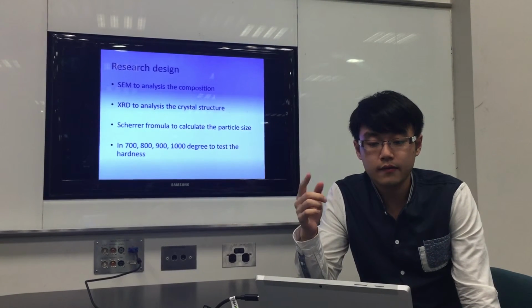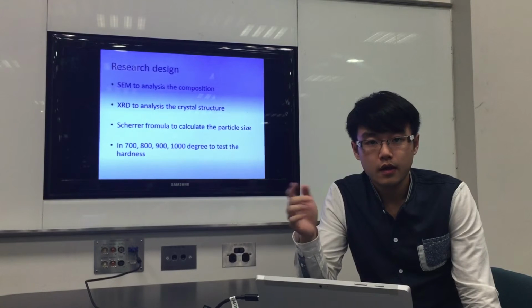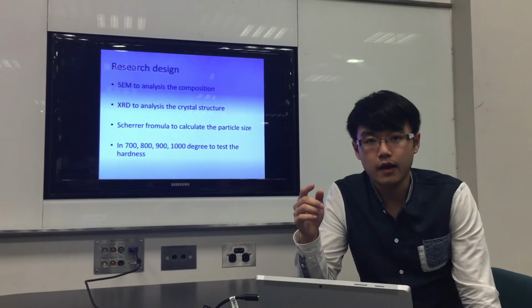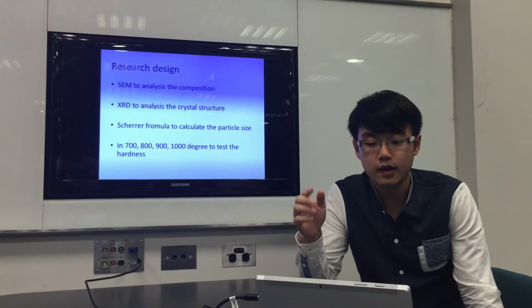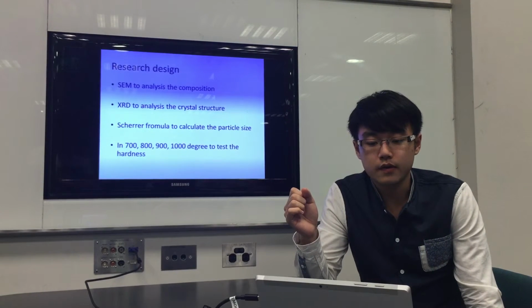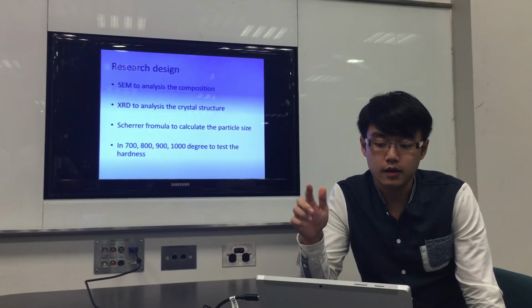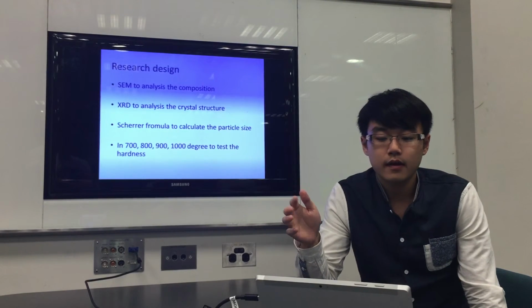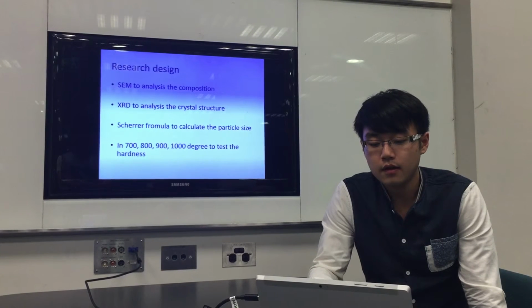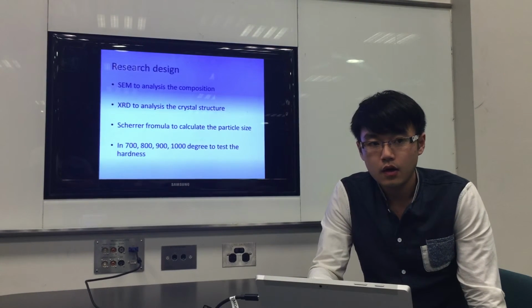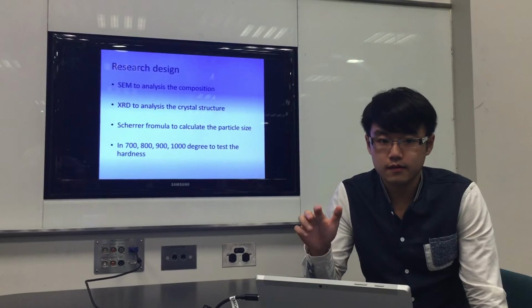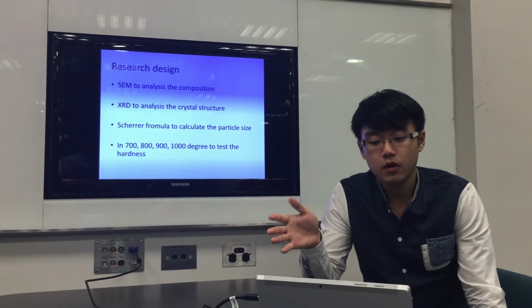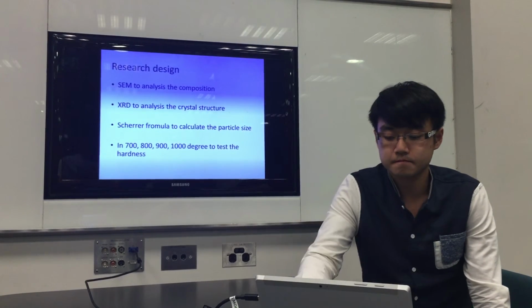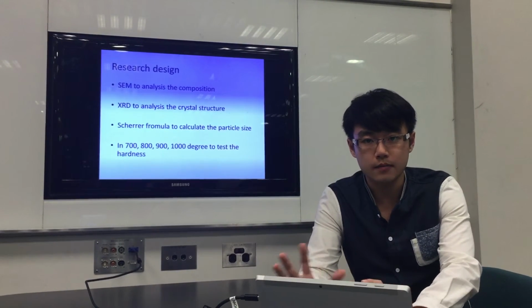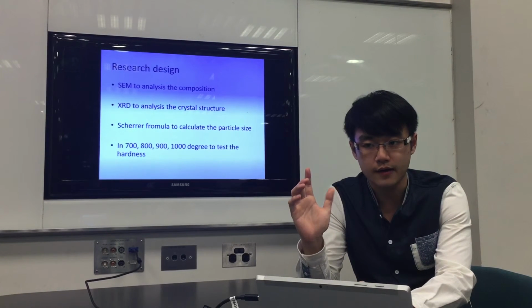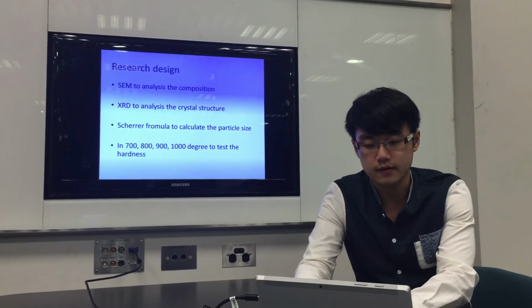First, I will use SEM to analyze the composition, and also I will use XRD, X-ray diffraction, to analyze the crystal structure. Then I will use the Scherrer formula to calculate the particle size, and also in environments of 700, 800, 900, and 1000 degrees, we will use the samples to test the hardness. From this test we can analyze the heat resistance.